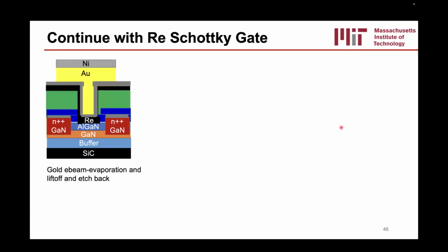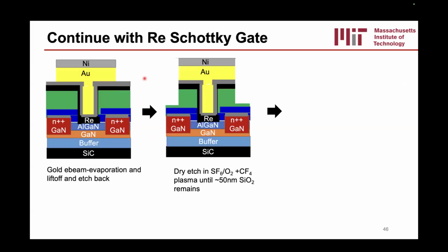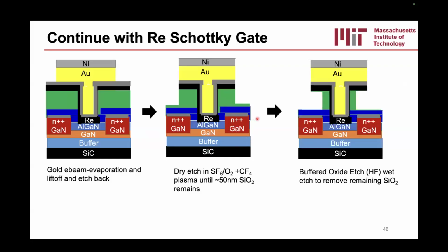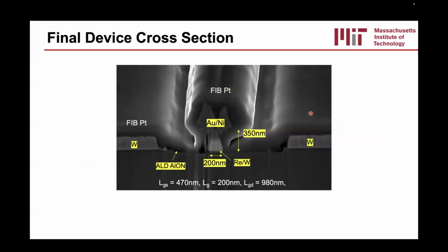All right, so then we can continue with this long process and finally use the nickel as an etch mask and etch down the SiO2. We leave about maybe 50 nanometers of SiO2 and then remove it in BOE just to make sure that we don't get too much plasma damage on the aluminum oxynitride layer that we use both as an etch stop as well as a passivation. And so at this point, the devices are complete.